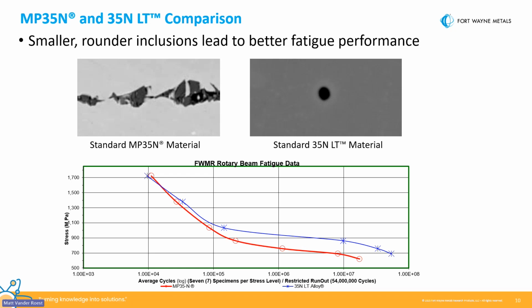So what the chart shows is at a given stress level, which is on the vertical axis, you can see that the trace for the 35NLT is to the right, and it is higher than the red trace for MP35N. And so what that shows is that at a given stress level, the 35NLT survives multiple orders of magnitude, up to 10x, more cycles than the MP35N. Or you can say at a certain fatigue life or a certain number of cycles, the 35NLT is able to survive a higher stress level than the MP35N.